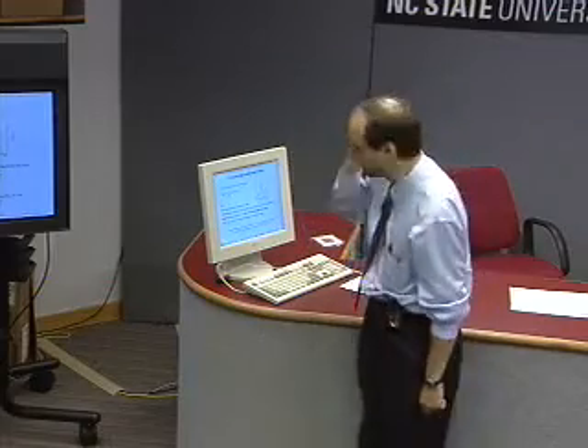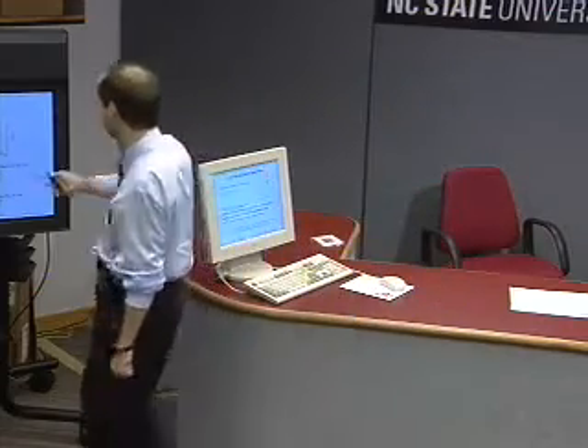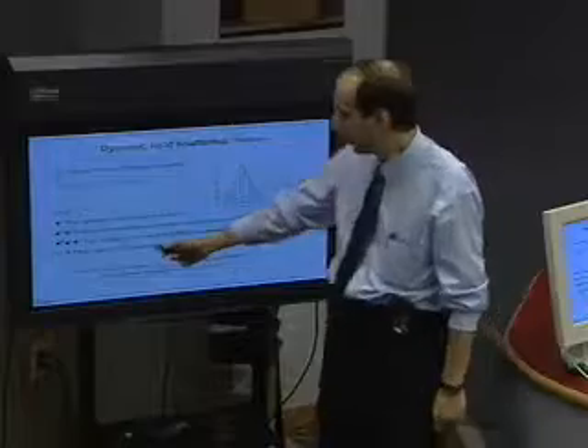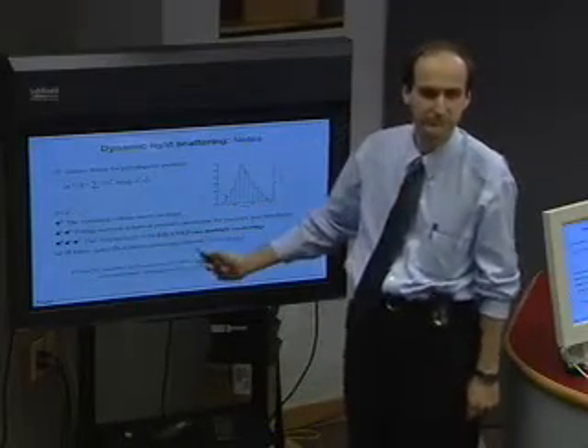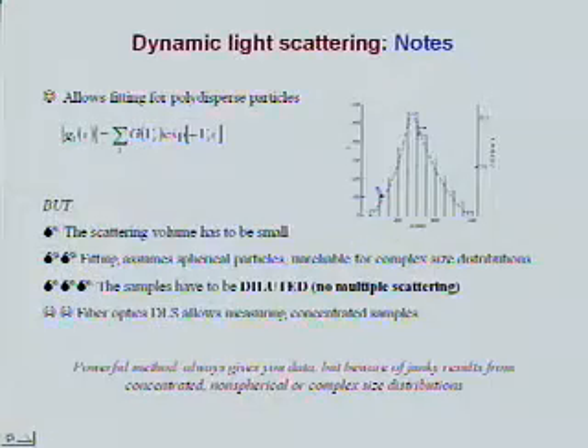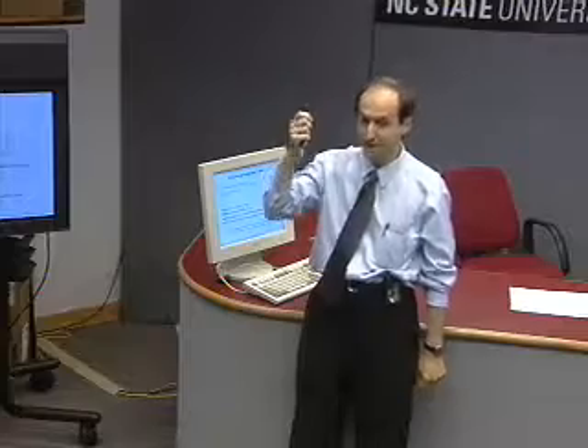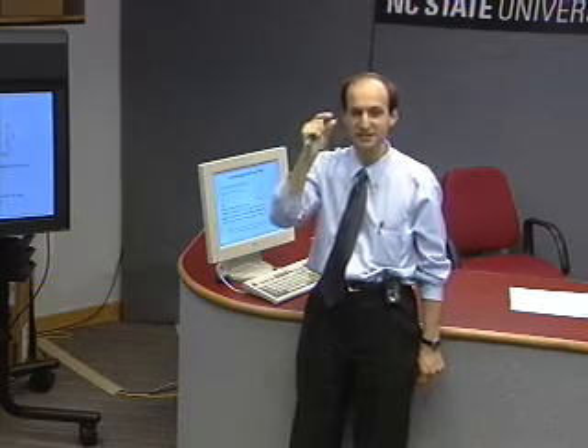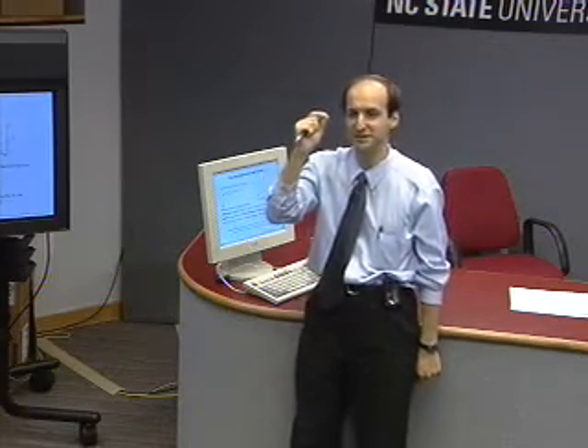And finally, the most common problem, this is really very common and very unpleasant. The samples have to be diluted, because this mathematical model assumes that you don't have multiple scattering. The intensity that you measure is intensity from single particles. It does not go through other particles which distort the data. Diluted means, from the practical viewpoint, samples which are almost transparent. Essentially transparent, you just see a very, very small translucency.